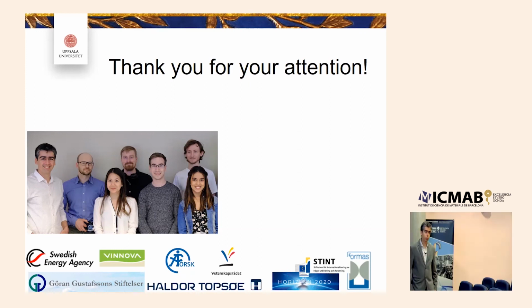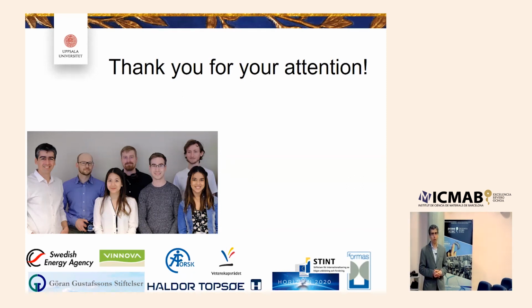About the use of TEP and LiBOB, what is the concentration of LiBOB and TEP you use? Because TEP, TMP are known to not be quite stable at low potentials. You could dissolve sodium BOB in TEP easily up to half molar, 0.5 molar. If you mix TMP or TEP with NMP, you can go even higher, like 0.8, 0.9, but not more than that. But in your electrochemical cells, do you use like 0.5 molar sodium BOB in TEP, for example?